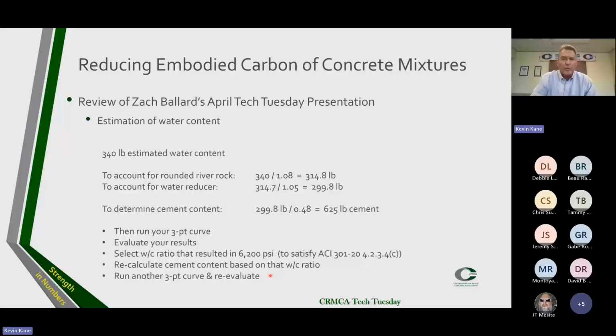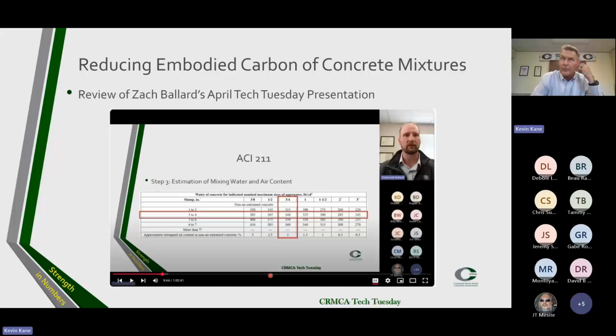A little pro tip too: you can avoid that whole accounting for water reducer if you choose to, instead of selecting, okay, let's say you needed to design a 4-inch slump concrete mixture. These table values are based on the water slump that's generated, not considering the water reducers. So in my experience, if you're using a type A water reducer, this is where you want to be, in this 3 to 4-inch water slump range. If you're using a high range water reducer, you could go down to a 1 or 2-inch water slump.